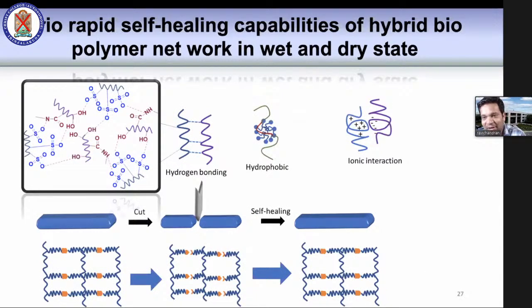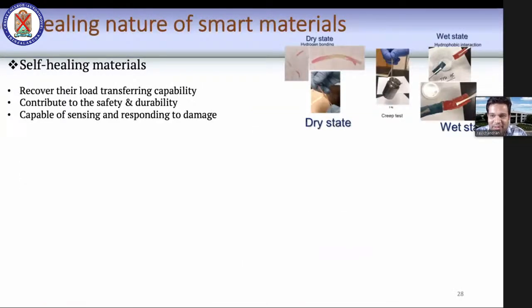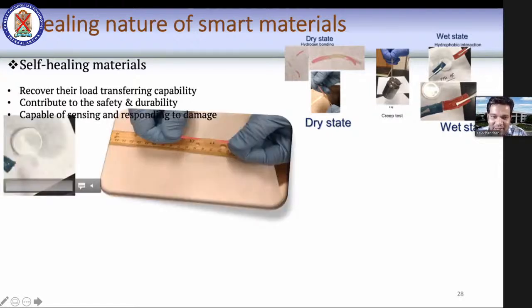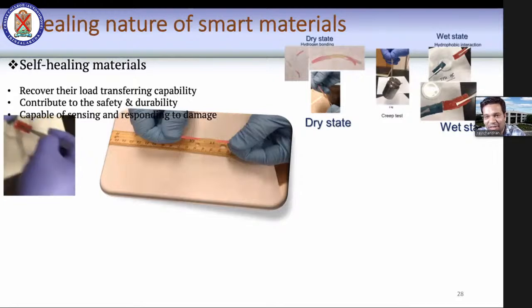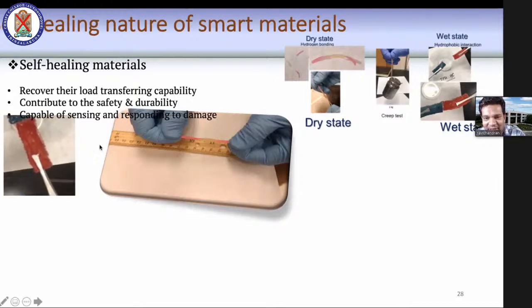They also created tri-responsive and di-responsive materials, creating a polymeric network with smart materials using azobenzene or spiropyran molecules, which can create hydrogen bonding interaction or hydrophobic bond interaction. When you break the material and keep it over time, from zero time to a number of days, it self-heals. So we created a dry state and a wet state. In the wet state, when you place the broken materials in solution, they form hydrophobic and ionic interactions, and can start to heal each other.